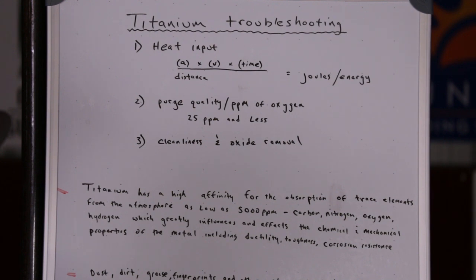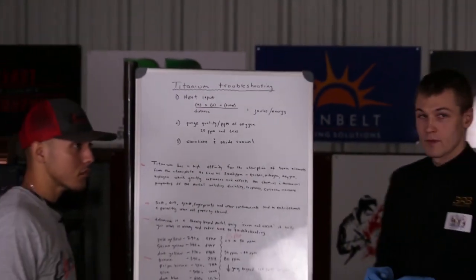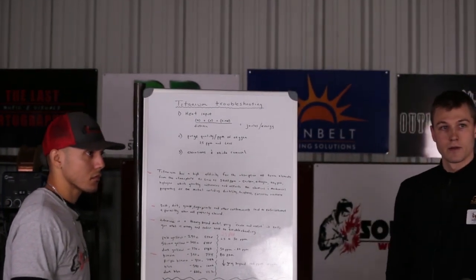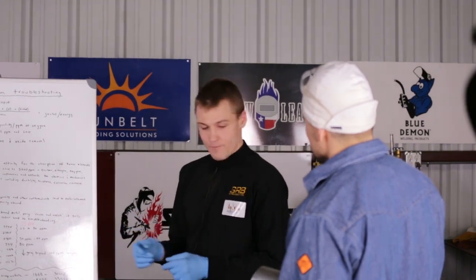And depending on the temperature that the metal is at, and depending on how many parts per million of oxygen are within the atmosphere that is interacting with the metal as it's at an elevated temperature, the material starts to form oxides, and different thickness of oxides depending on how hot it is, and how many parts per million of oxygen is interacting with it. Okay. So you're saying that the amount of oxygen affects the color of my weld? Yeah.